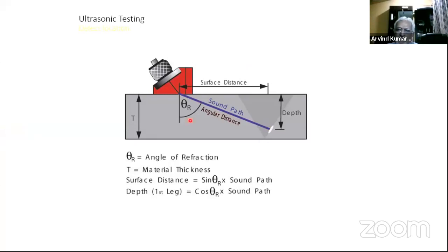Again, the calculation of surface distance, as I said, is sine theta times the sound beam path. Sound beam path is what the sound travels inside the material before hitting a defect, the total travel, which we call the sound beam path. And then the depth we can find out using cos theta and the sound beam path. Again, depth is from the top surface, how deep it is. If it is a direct hit, fine; if it is after a bounce, then you have to remove one thickness from that.